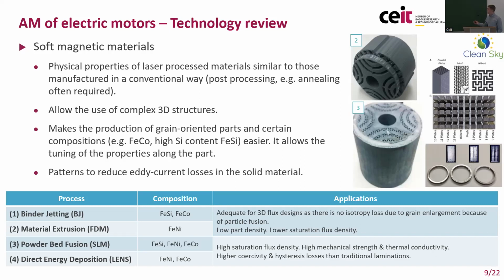What additive manufacturing allows, on the one hand, is to have quite complex 3D structures, the ones you can see in the pictures, and also it makes the production of some particular compositions maybe even easier than for traditional manufacturing, for instance, of high silicon content iron alloys or iron cobalt alloys. So regarding the additive manufacturing of soft magnetic components, results for the moment are quite good.